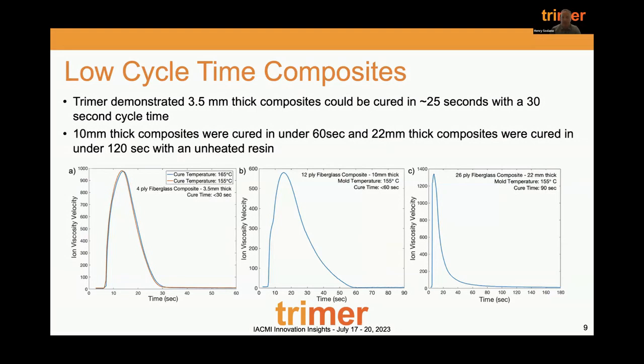So as the polymer is being cured, let me just show you what's happening here. This first 7 seconds is the press closing and vacuum applied to the compression tool. As the resin comes in contact with the center and the temperature of the resin is increasing, you get a viscosity drop once you get better ion mobility. It reaches a peak, at which point we're starting to cure the polymer, lock up the material, remove ion flow, and then it'll drop down, and when it reaches baseline again, you're fully cured. And so in this case, at 30 seconds, given this 7-second press closure, we've cured that polymer in 23 seconds. So extremely fast cure rate.